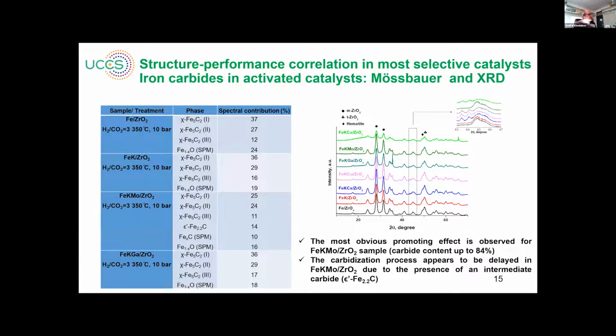Then we did characterization, and what we found. First, this was conducted in situ with Mössbauer spectroscopy to study the state of iron. What we found is that all catalysts contain a significant amount of iron carbides. However, the highest amount, as we can see here, was obtained for the potassium molybdenum catalyst. We also see the presence of iron carbide by X-ray diffraction of the spent catalyst. Here you see the peaks, which correspond to different types of iron carbides. So it means that the iron under reaction conditions exists in the form of iron carbide.